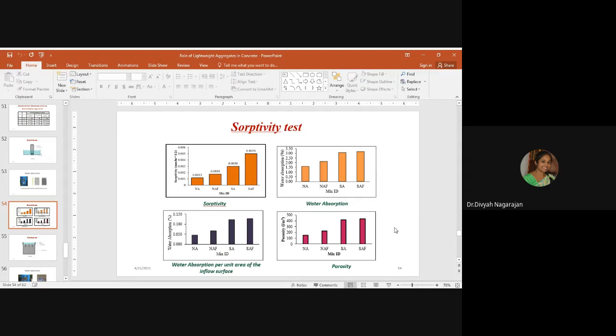On the contrary, the inclusion of the fiber increases the mechanical properties, but it did not affect or reduce the porosity of the concrete. Further, these fibers indirectly or a little bit induced the water absorption of the concrete.